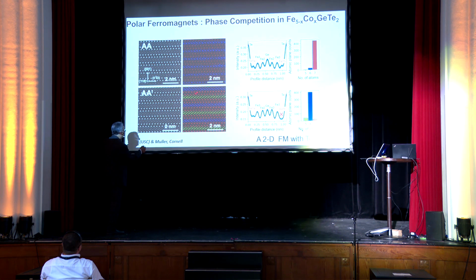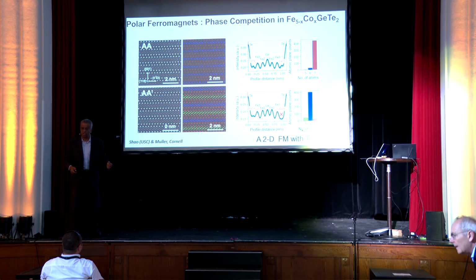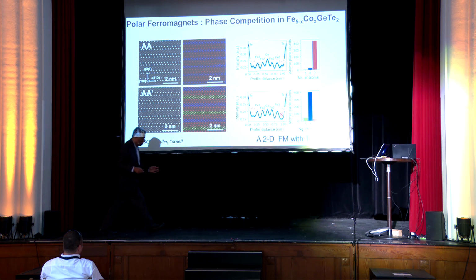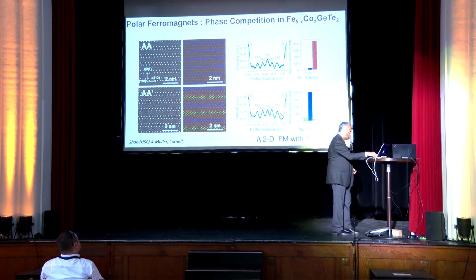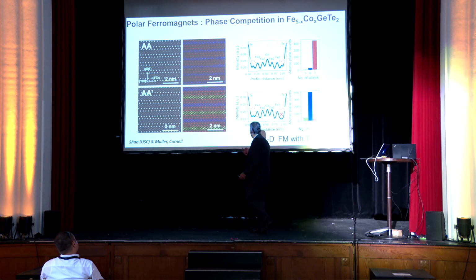At the 50% cobalt doping, you can see it goes into this green, blue, zigzag structure. At the same time, it goes from 7 layers to basically a 6-layer sequence. And you automatically know there is something that's breaking symmetry there. So in this particular system, you can follow the broken inversion symmetry at the atomic scale. So the key question is, why is it that putting cobalt into the system breaks the symmetry? Now, there's a lot of electronic structure calculations that's happening, but we don't have conclusive proof yet as to why the system goes into that phase.